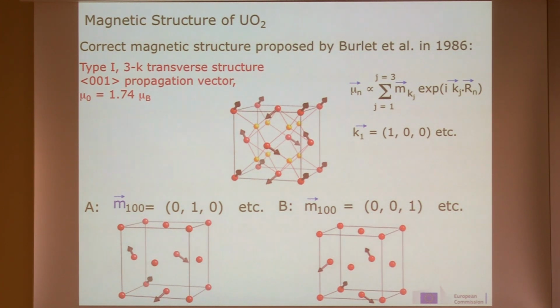They observed no variation, so it was a zero observation experiment, and then the possibilities were two. Either the structure was a triple K, where the magnetic field has no effect on the diffraction pattern, or the magnetic field was not strong enough to reorient the system.